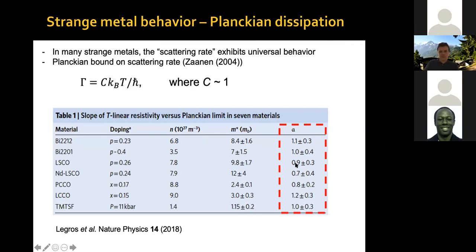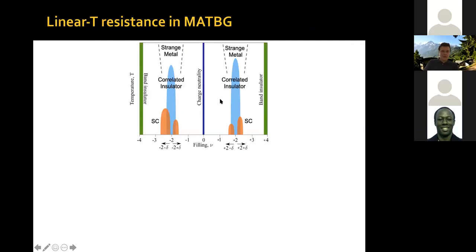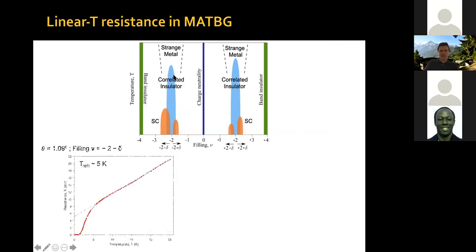Okay, so now in this phase diagram of magic angle graphene, I told you there's this region of correlated insulator behavior and nearby superconducting domes. If you take a magic angle graphene device, this one is one which has a relatively high TC, so the system goes superconducting already below a few Kelvin, okay? But if you go above that superconducting transition, you see that the resistivity from then onwards is very linear, okay? And it's very linear up to temperatures, in this case, I only show 25 Kelvin.